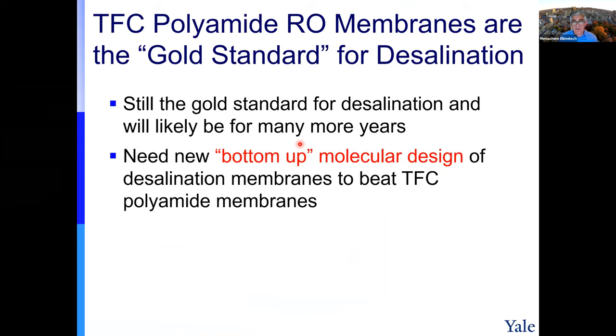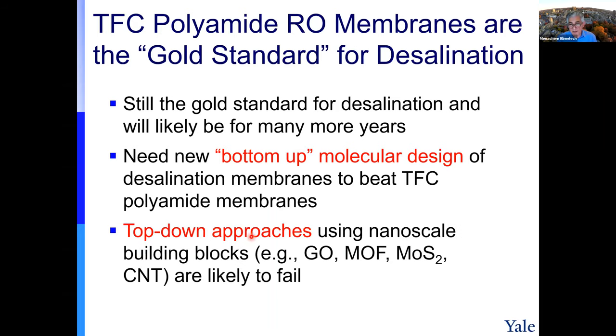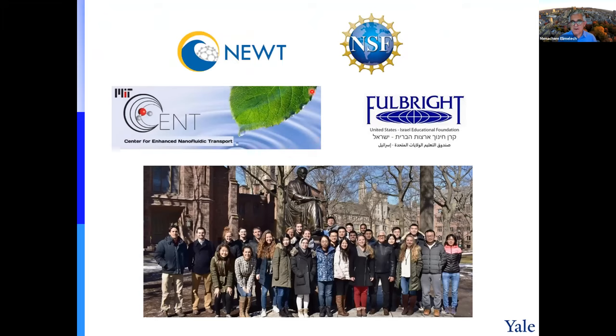In my opinion, if we really need some membrane, we cannot use the approaches that I showed you earlier, which are top-down approaches. We need to use bottom-up approaches, molecular design, that you have some molecules that interact and you create the structures and the pore that you want, as opposed to all the other membranes that you already take existing structures like GO, MOF, MoS2, et cetera, and you hope that by putting them in such a way that they will arrange perfectly with no defects, it will not work. You need bottom-up approach.